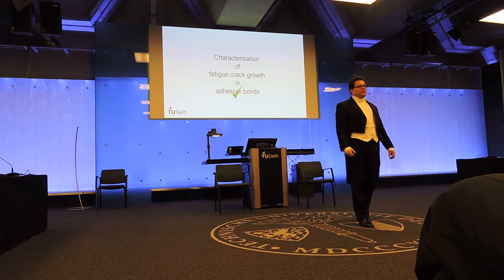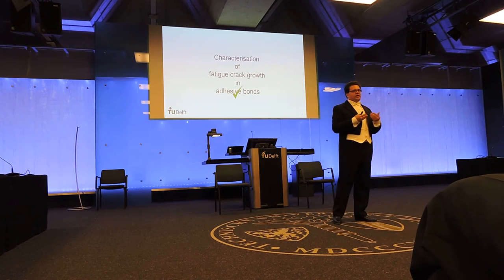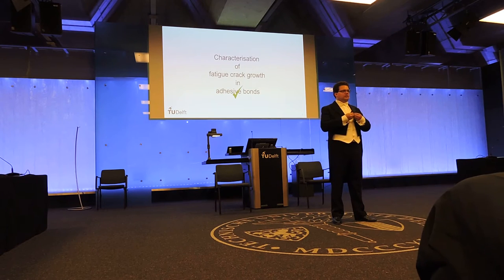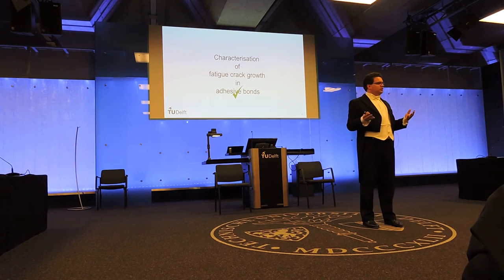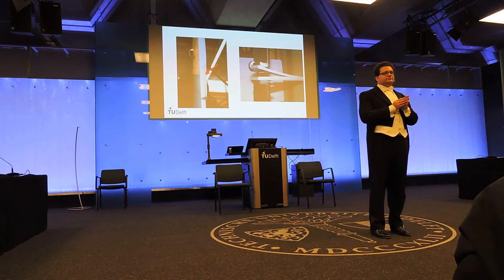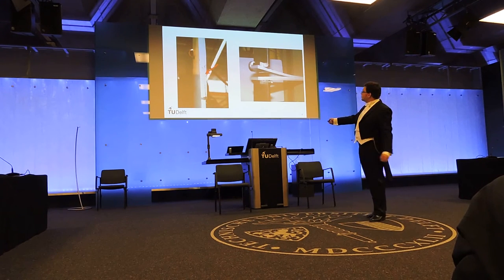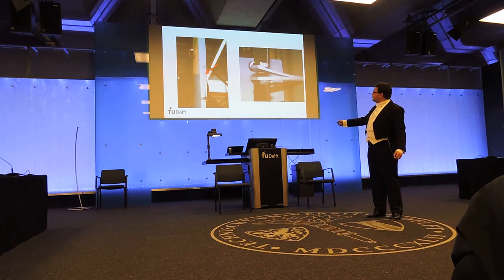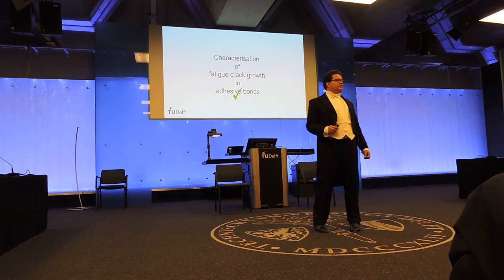Then the next term: fatigue crack growth. What does that mean? Well, in a structure you have repeated loads — you're pulling, letting go, pulling, letting go, lots and lots of times. Cracks can appear in the structure, and over time they will grow. Each time you have one of these cycles of pulling and letting go, the crack will grow a little bit further. In order to predict how long we can safely use the structure — how long it will last — we need to predict how far and how fast the crack will grow. A small crack is not a problem, but if the crack grows too large, your parts start to separate and eventually might fall off, which is bad. Here you can see a plate with a crack running all the way across, and here two aluminium plates glued together with a large crack. So that is fatigue crack growth — we want to be able to predict it.